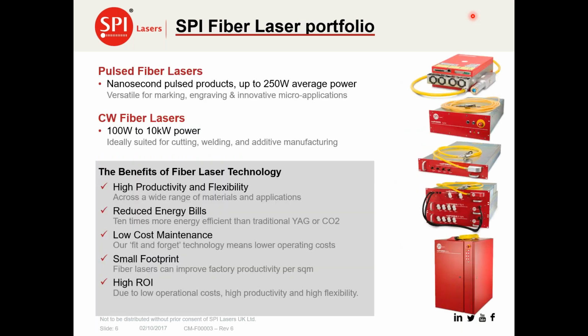In terms of lasers, there are two basic types of fiber laser that we supply. Those are pulsed fiber lasers, which are nanosecond type pulse products, which currently are available up to 250 watts of average power. These are MOPA type lasers that give us a lot of control in terms of the pulse characteristics, enabling us to vary the pulse duration from as short as 3 nanoseconds up to 2000 nanoseconds or 2 microseconds.